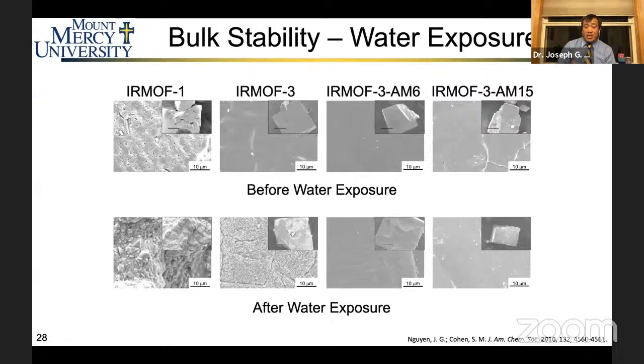You can see here with IRMOF 3, when I add water to it, the surface starts to break apart. With the AM6 and the AM15 version, especially the 15 version, notice that the surface hasn't really changed very much. You can see a little bit of change with the AM6 version, but nonetheless, the electron microscopy helps visualize how well we've stabilized these MOF structures and given them some hydrophobic properties.